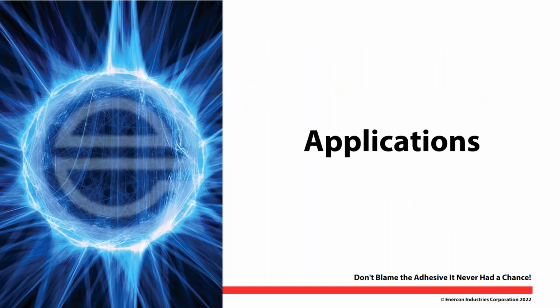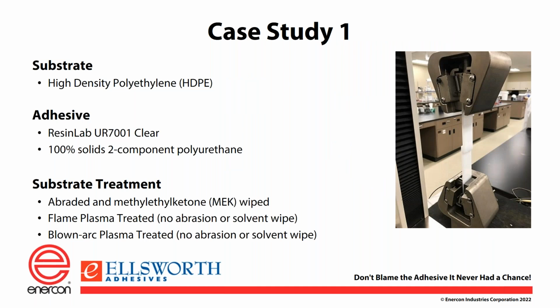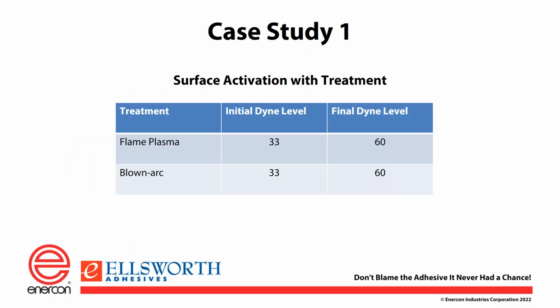So let's look at a couple of applications. This was a case study that we did with Resin Lab. We were using high density polyethylene with a clear Resin Lab adhesive. We put these together and then we did a pull test on it. We did clean it first, and then we tried the flame plasma treatment and the blown arc treatment to see what gave us the best results. And then the one sample that was not treated was just cleaned first.